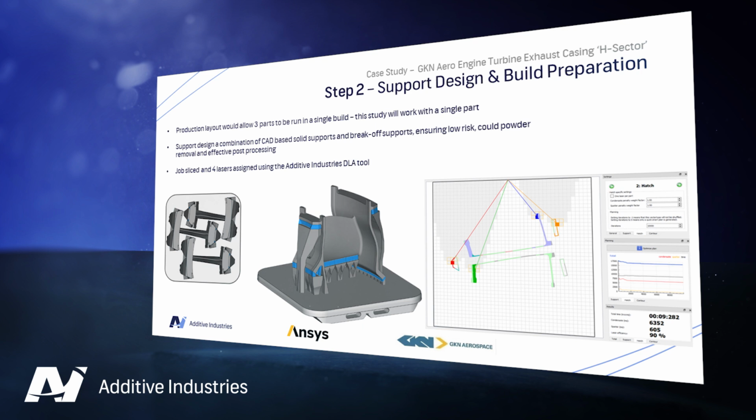Once we've set up the build, we assign the process parameters, slice the build, and then because we're building a single large component, we're able to utilize our Additive Industries dynamic laser assignment tool. This tool allows us to assign up to 4 lasers to a single geometry very effectively, taking into account all of the quality and productivity factors that you need to, such as the gas flow, the spatter formation, all of these things. So this is processed in the conventional manner, and then we can move to step 3 of producing the test part.